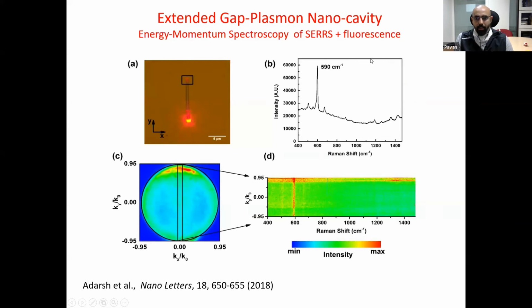If you integrate over all momentum vectors, you will see that the Raman scattering signature is quite intense. Now, if you take the same light and distribute it in the momentum space using the back focal plane technique, then you get the distribution in the K space, but it is still integrated over all wavelengths. Now we take a small part of this momentum space and then do spectroscopy in that.